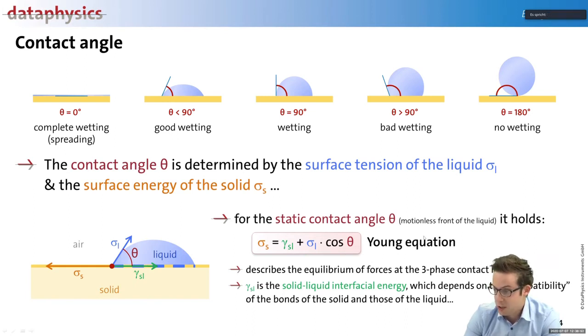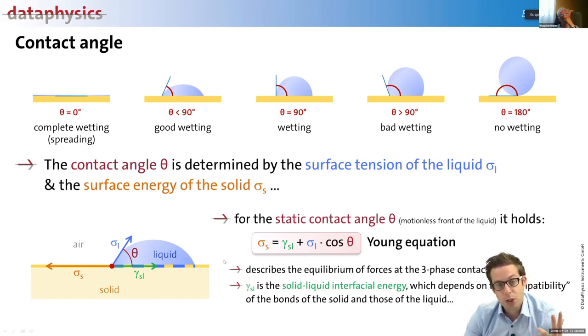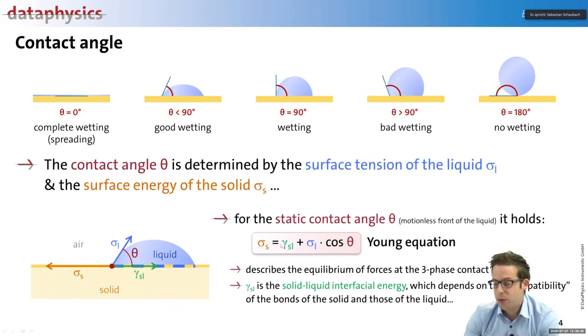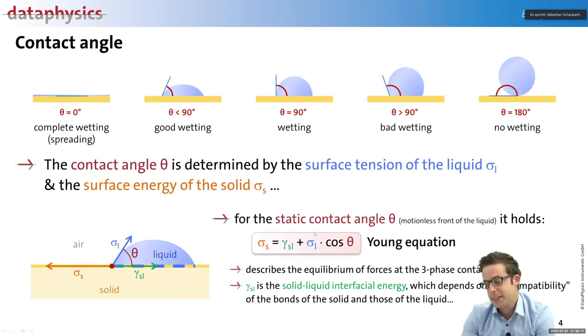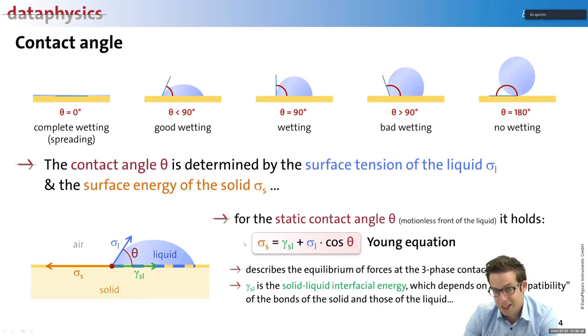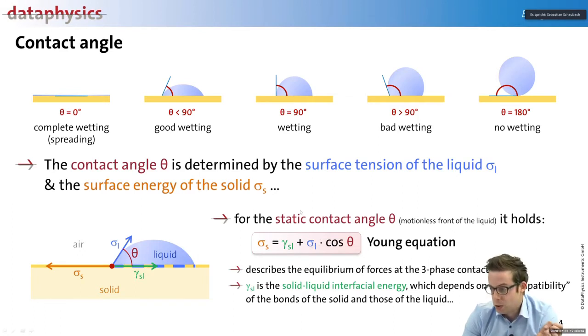The contact angle also teaches you about liquid-solid interaction through the Young equation. You have sigma-S, the solid surface free energy — a property only of the solid material — the surface tension of your ink, a property only of the liquid phase, and the solid-liquid interaction term, which tells you about the interaction between the liquid and solid phases. The contact angle plays an important role here. Contact angle, surface free energy, and sigma-L surface tension can all be measured and calculated to characterize the interaction between your liquid and solid material.